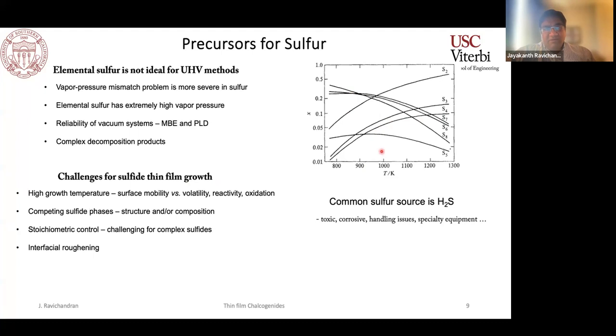And on top of it, invariably, some of the common sulfur sources, which are a little more reactive and can be implemented a little bit more, tend to be much more toxic, corrosive, and lead to lots of issues in having a very reliable growth process. One example is hydrogen sulfide, which is always considered a little more reactive than the elemental or molecular sulfur, but puts a lot of stress on the type of vacuum equipment and the monitoring that you do for pressures and so on and so forth.